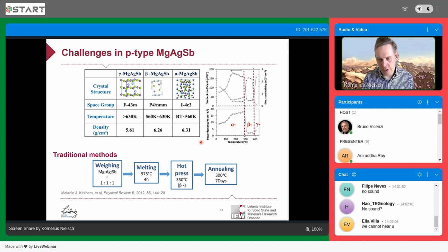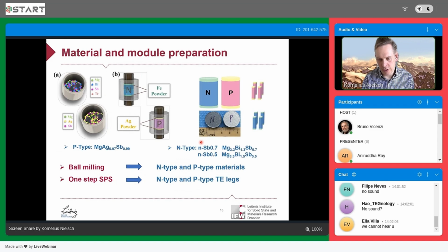Therefore, the whole processing has to be kept in mind, so that you don't produce the beta phase material but the alpha phase material, but we can control it quite well for our applications. On the other hand, if you take stability into account, the typical bismuth telluride modules can operate up to 200, 250 centigrade. So magnesium silver antimonide can still be used at slightly higher temperatures than bismuth telluride.